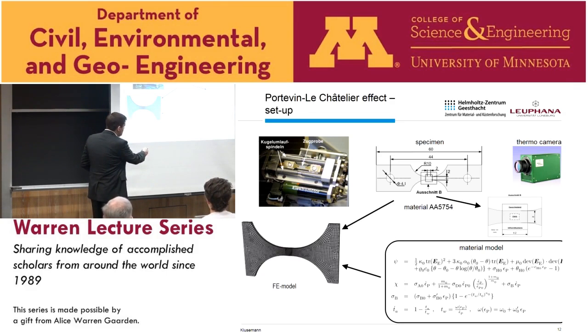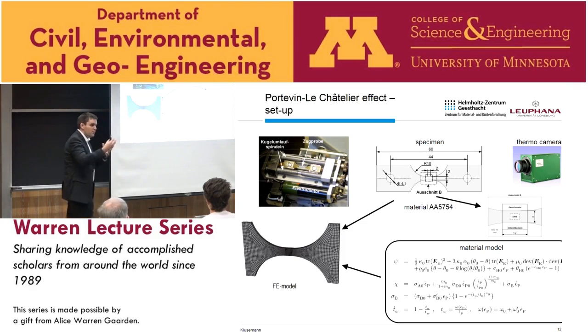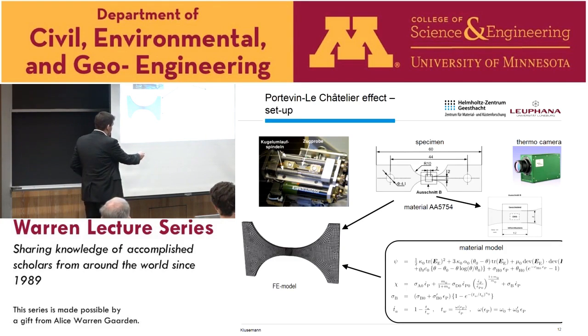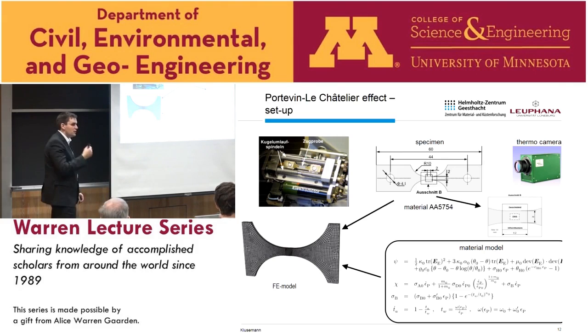And for that reason, we formulated our free energy density, which is very classically just the elastic part accounting for temperature effect, plus then some hardening contribution. For the hardening contribution, we simply assumed a kind of Voce hardening. Then, of course, we have the dissipative effect, which is given by the dissipation potential. So we have a classical activation form, plus this power law relation in terms of the plastic strain rate, plus a term which is now contributing to the PLC effect. This is a Cottrell-Bilby-like stress contribution.